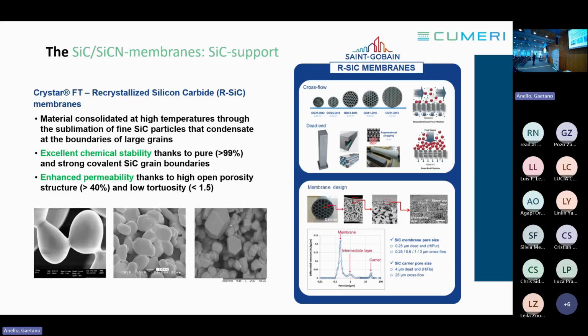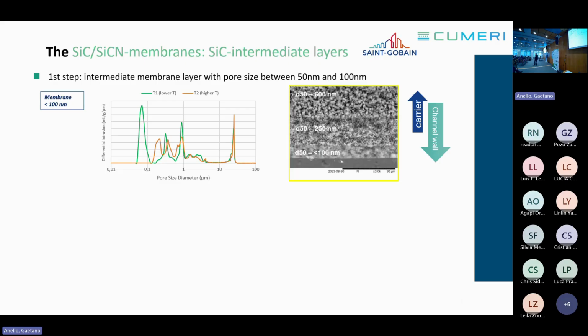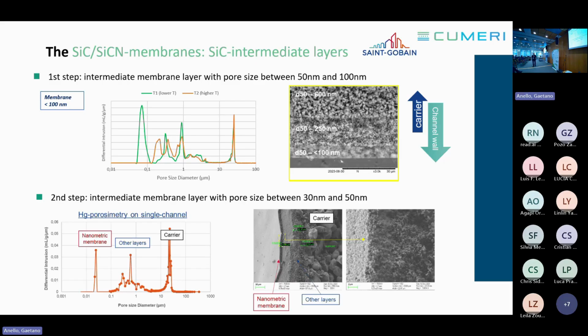As I mentioned, the pores are too big to coat directly with the polymer. Therefore, they first had to try to reduce the pore size of the last membrane layer. In the first step, they reduced the sintering temperature for the final layer. By doing so, they made an additional final layer and treated it at a lower temperature, and they could reduce the pore size of this layer to below 100 nanometers, anywhere between 50 and 100 nanometers. Very nice, but it's still not enough. Therefore, they made a second step with a slightly different precursor material. By doing so, it was really possible to get a membrane layer with a pore size in the range between 30 and 50 nanometers. This is very nice, and also quite interesting for Saint-Gobain, because now they have a new kind of membrane that can also be used in liquid filtration.